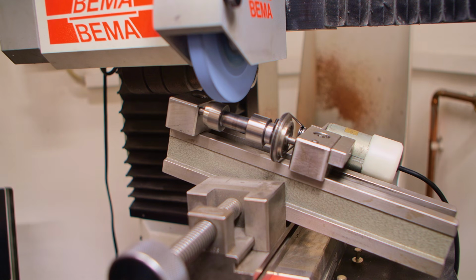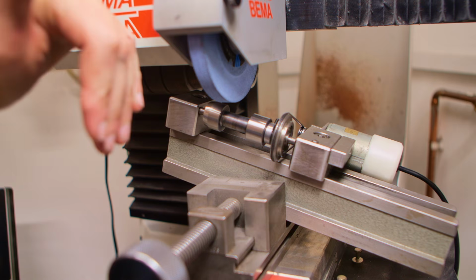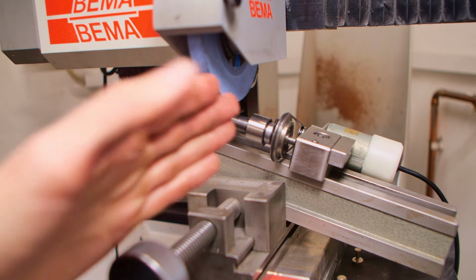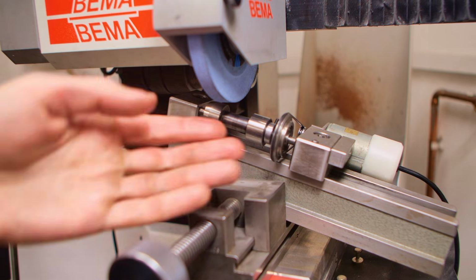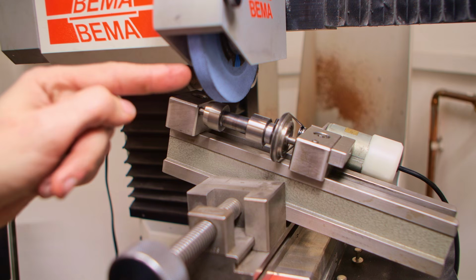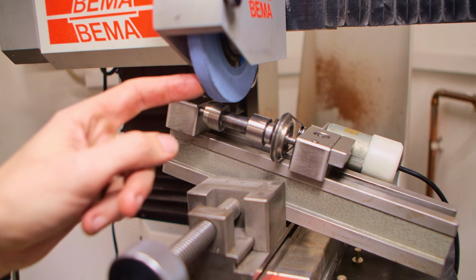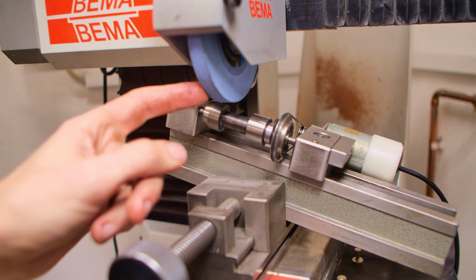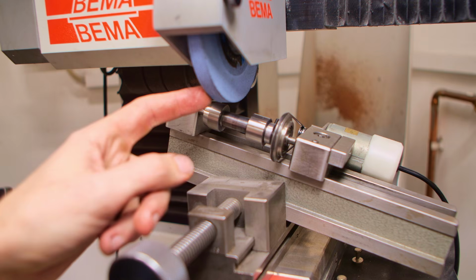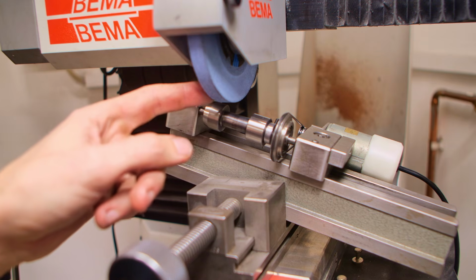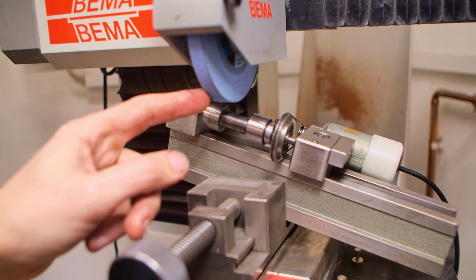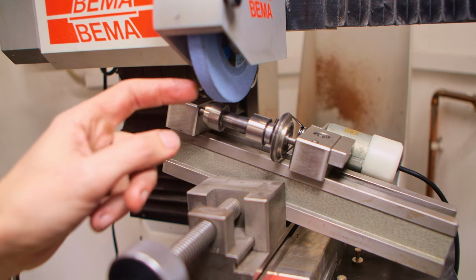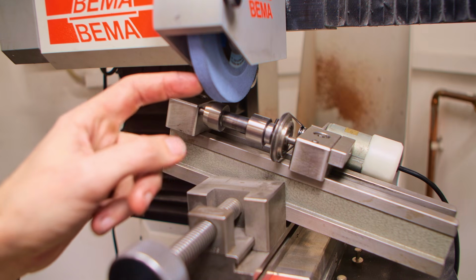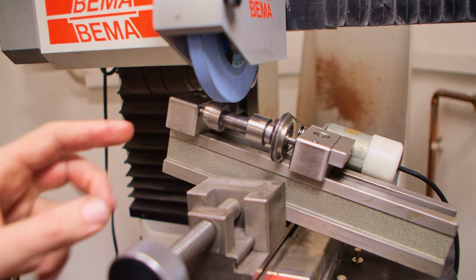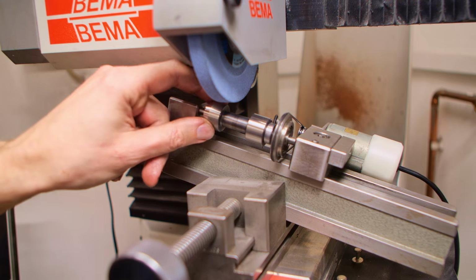You see how quickly that goes. I'm taking 50 micron downfeed passes, and then I'm feeding the edge of the wheel across the part. The edge of the wheel is doing all the work. This is a Norton 3SG seeded gel or ceramic grinding wheel, and the edge on these holds up really, really well. This is really my preferred wheel on such a light duty machine for round work.